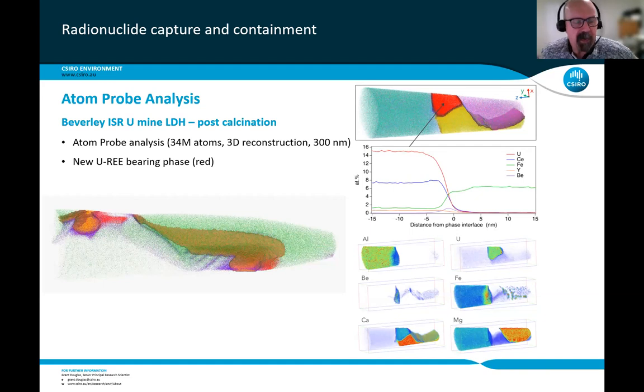Okay, if we have a look at the atom probe analysis that we conducted on this sample following calcination, this is 34 million atoms in these individual images, and this is a 3D reconstruction. The spike that you see here is around 300 nanometers long. What we can show, and I won't go into great detail, is that we've got an interface there where we've mapped across that top right-hand image. And so we can see uranium declining across that interface. We can also see in the blue cerium, one of the rare earths, declining across that interface. And as we cross to the other side, we've got iron increasing, which tells us that we've gone into a spinel phase.